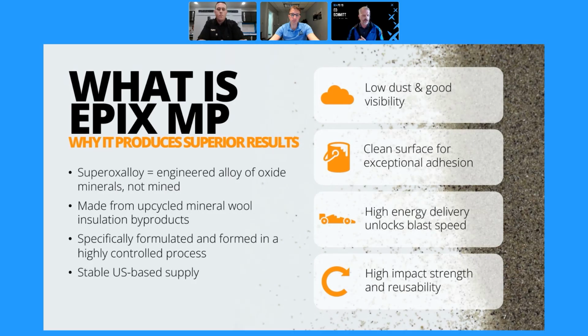In a smaller cabinet, we were doing work with a customer that was blasting tungsten, and they were using silicon carbide, which is also a very aggressive media. When they switched from the silicon carbide to the EpiX material, their bond strength went way up. They resolved an issue that was causing a lot of rework, and were able to get that cleanliness level in a fraction of the time. After they made the switch, they reached out later and said that they were seeing extended gun life, and were using fewer consumables in the blast process.